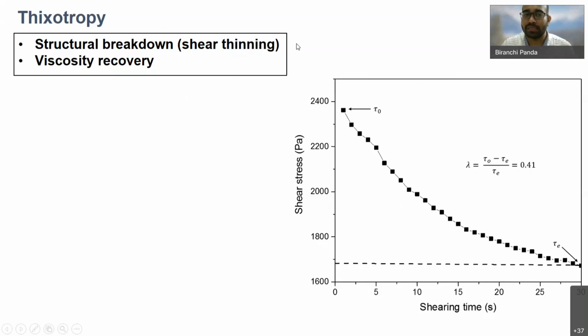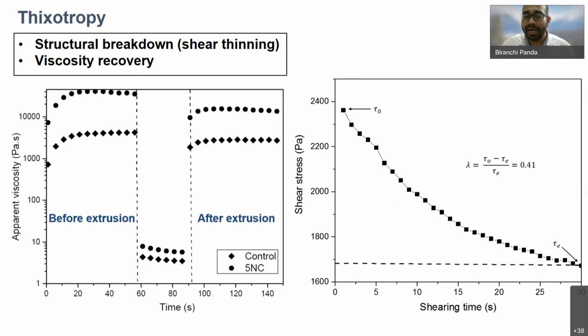Now, once you deposit the material, it is very important to measure viscosity recovery. So what is viscosity recovery? It is very clear that during pumping, we need a very low yield stress or low viscosity material. But the same viscosity cannot be there once you deposit the material on the print bed, because with such low viscosity the material will simply flow away. So we want the material to recover its original viscosity. What is original viscosity? It is the viscosity at rest, before you pump the material. You mix the material, put it in a chamber, and measure the viscosity. But during pumping, because of the high shear rate, the viscosity went down to a very low value.